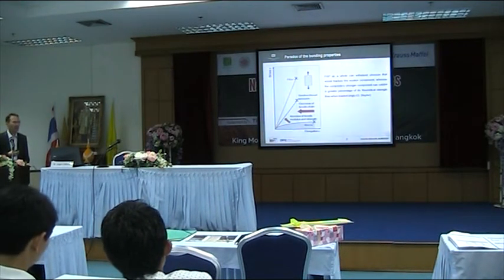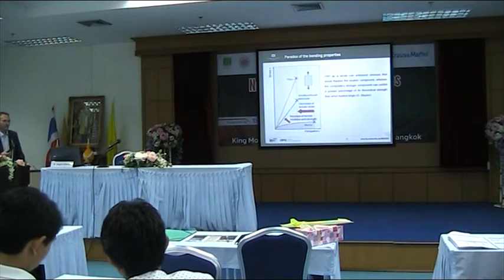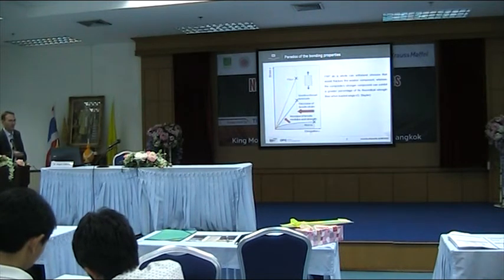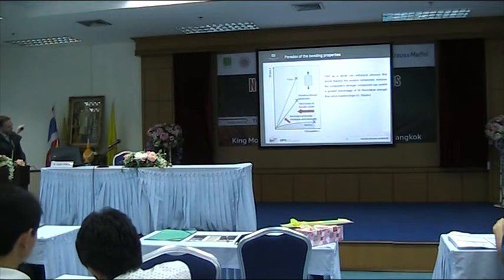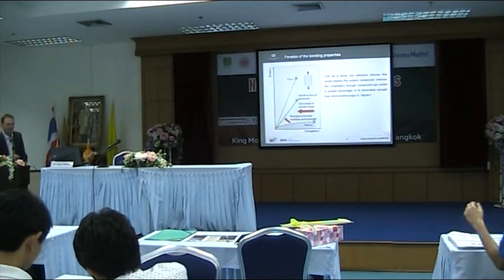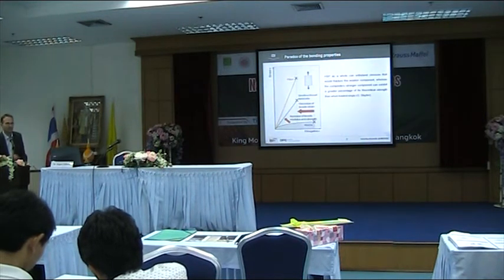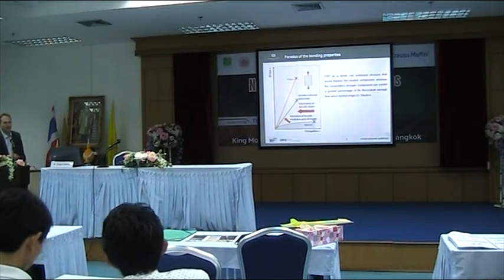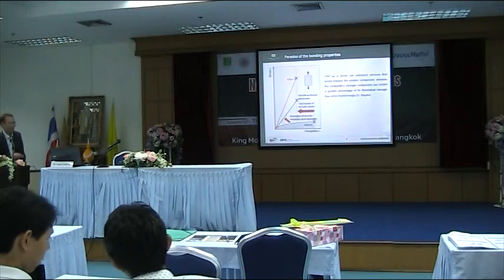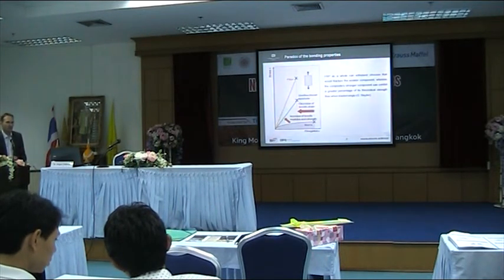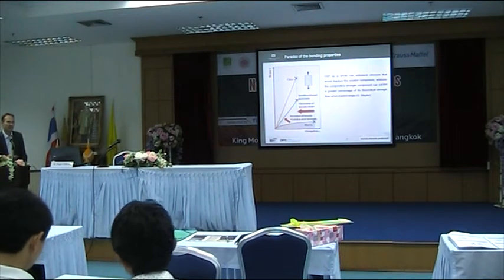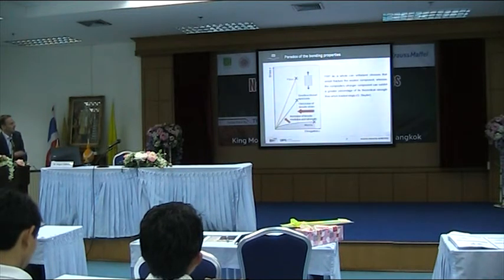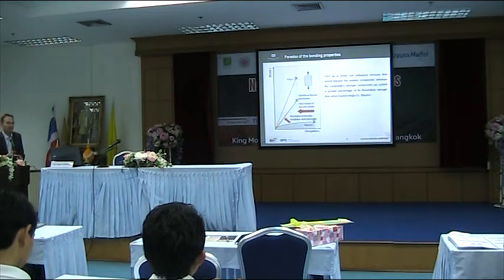Okay, now when we look at a fiber, and this is something typical for glass fibers or carbon fibers, but also valuable, with other qualities, for natural fibers, we have a matrix. Well, the matrix is weak. If you only have a matrix, for example thermoplastic polypropylene, you have a tensile modulus of 2000 MPa, so it's not so much. When you have a glass fiber, you can reach around 70,000 megapascal, and in the composite you have something in between. This is especially valid for the tensile modulus, and also for the tensile strength.